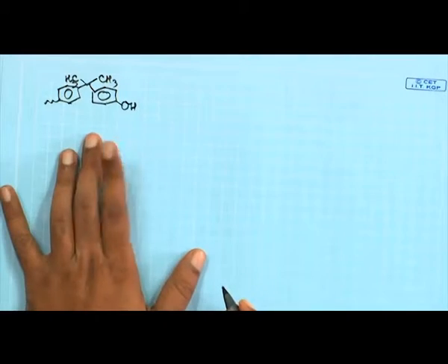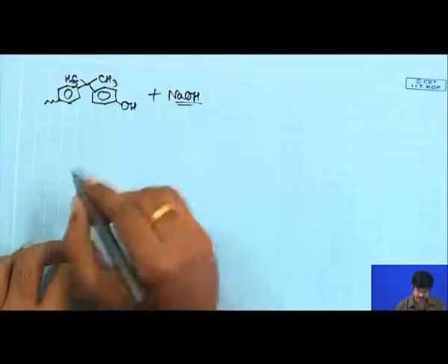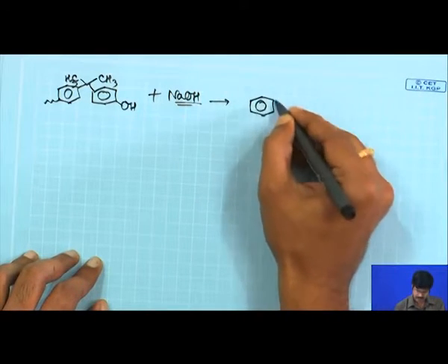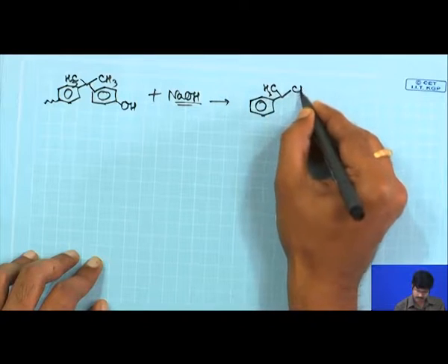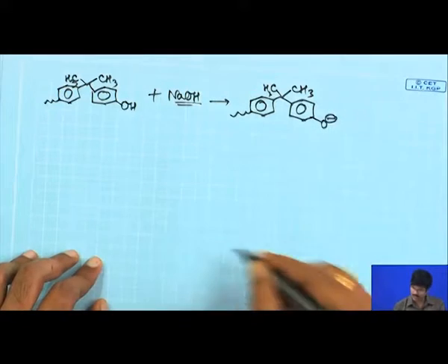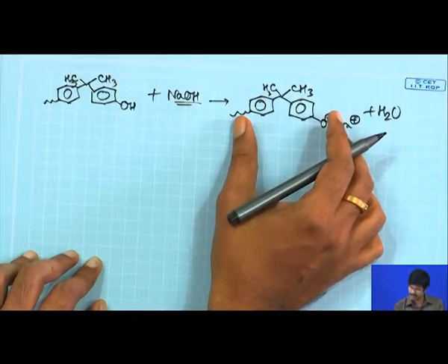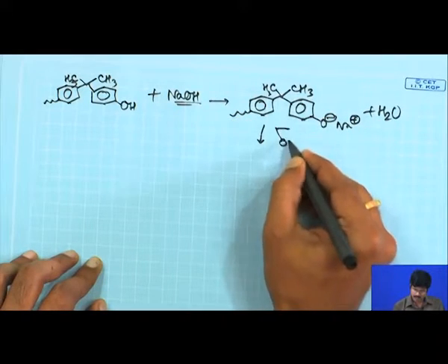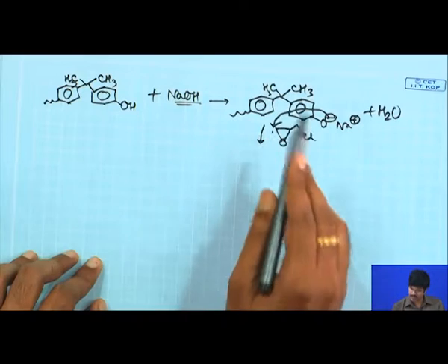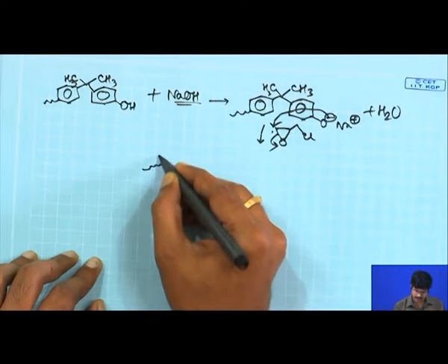All right. So, this reacts with sodium hydroxide. This acts as a catalyst, and then you will have O minus Na plus, and then water that is produced. Now, this reacts with your epichlorohydrin. So, of course, this will attack on this side, which is the less hindered side, and this will open this up. So, ultimately what you will get is the following.